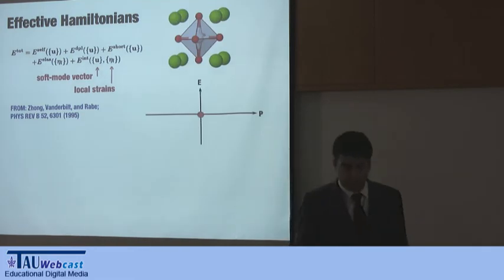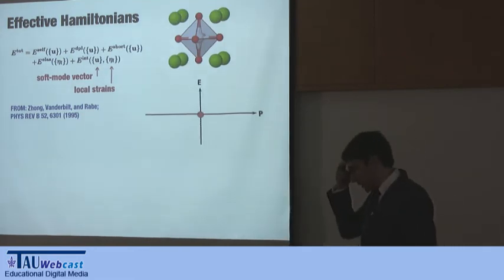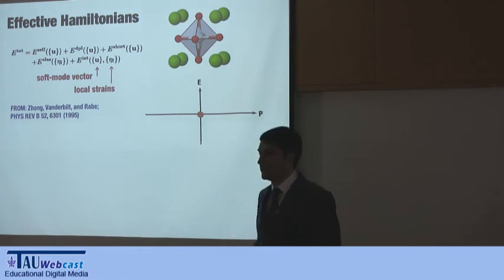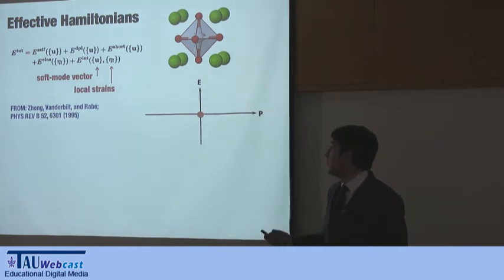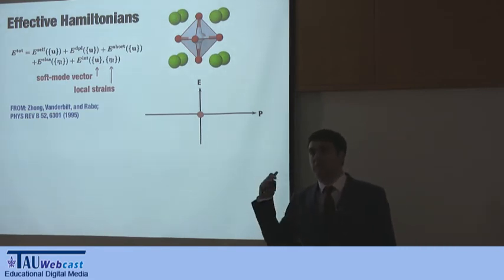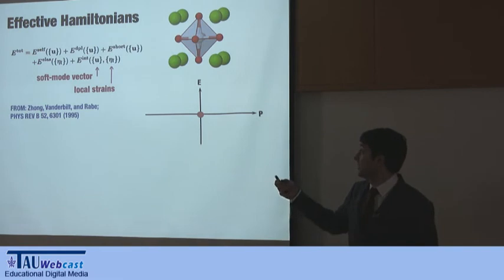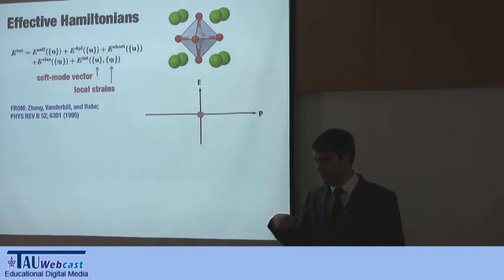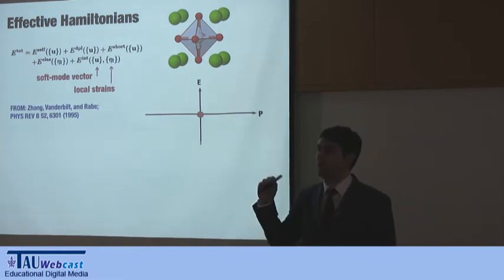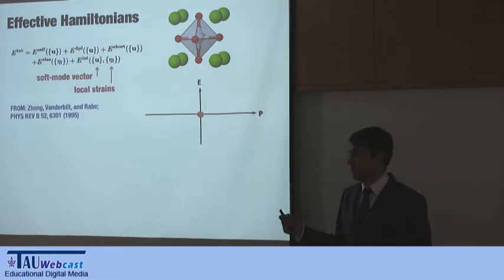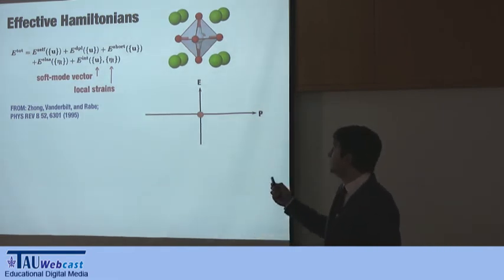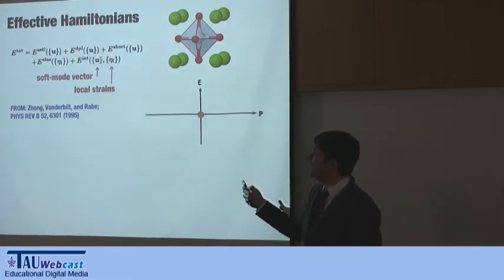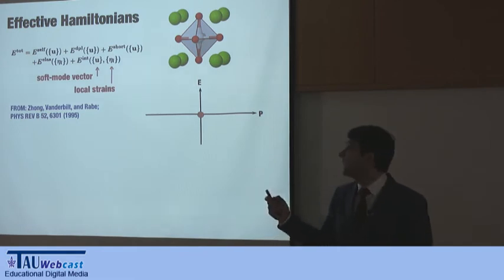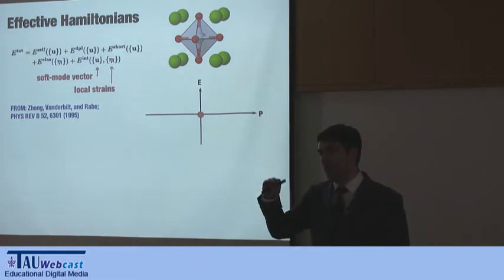So what is the soft mode vector? It's a concept that is very useful in seeing transitions in ferroelectrics, like barium titanate. You can see the transition that I show from the cubic. The cubic phase is the one at high temperature, and the polar one is the one that occurs below 130 Celsius, as I said. So you can see that there is a mode, there is a phonon in this structure, in the perfectly cubic one, that becomes soft as you lower the temperature.